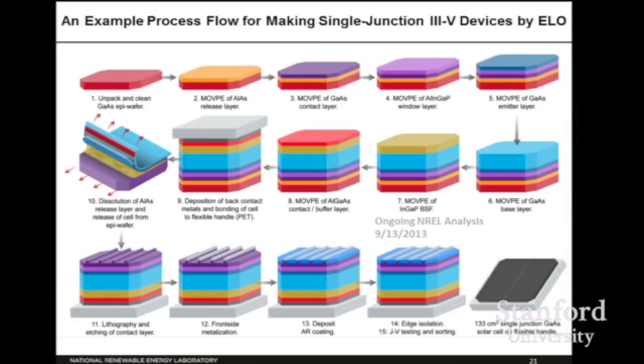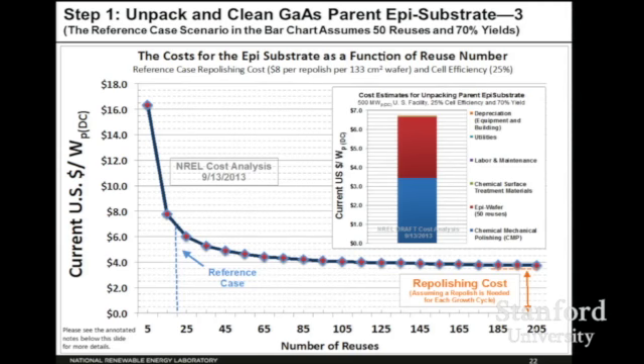And what they do is they come up with a process flow. They take into account every single step in the process, and they figure out what it's going to cost. And I'll just show you an example for one of the steps, which is one of the most critical steps. So this is the cost for the wafer itself as a function of how many times you're able to reuse the wafer. And they don't even start it at 1, they started at 5. If you could only reuse the wafer 5 times, the wafer's contribution to the cost of the cell would be $16 per watt. And let me remind you, our goal is 50 cents per watt for everything. And this is just for the substrate alone.